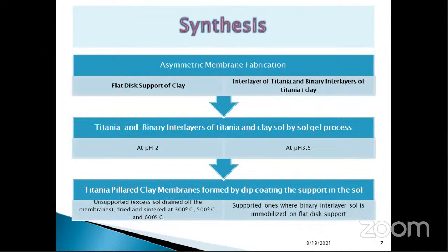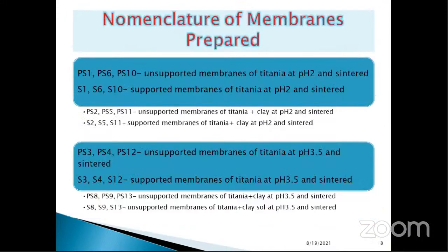So this is the entire synthesis procedure that has been shown as a flow chart. We can see the flat disk support. Then over there is the interlayer of titania and binary interlayers of titania and clay. Two different pH values were chosen, pH 2 and pH 3.5, which gave the titania pillared clay membranes that were formed by dip coating. That was used for the membrane rejection test. These are the nomenclature of the different membranes that were prepared. We prepared around 24 membranes, out of which 12 were supported membranes and 12 were unsupported membranes.